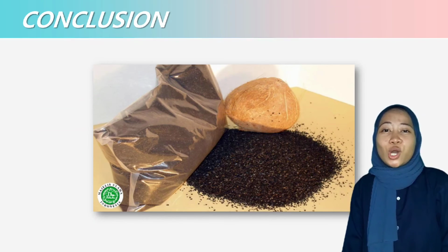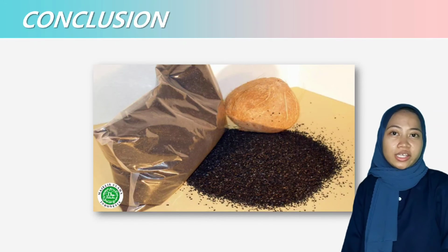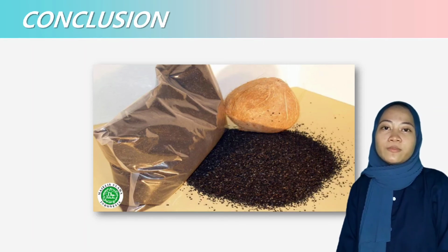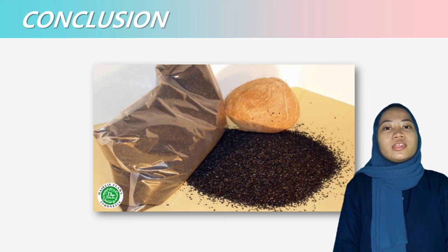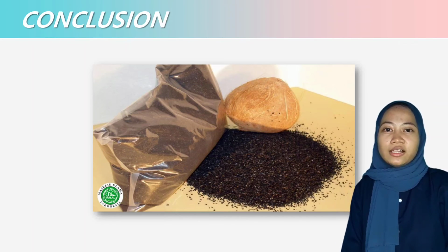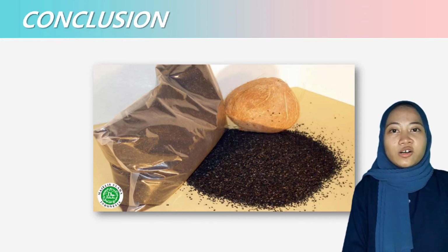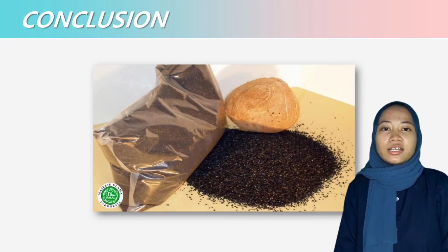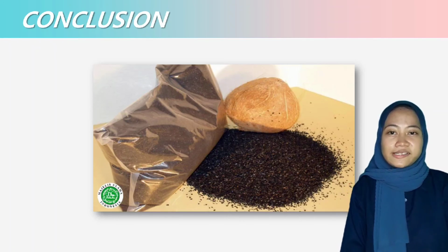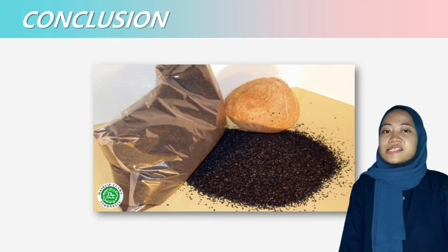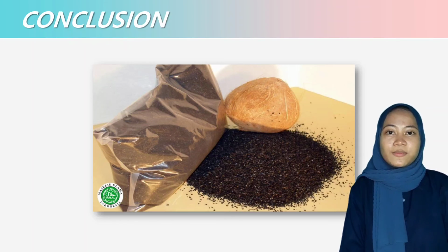So, it can be concluded that the highest efficiency of BOD, TSS, and turbidity removal is achieved by using 300 grams of coconut shell activated carbon for 7.5 minutes. The removal efficiency of BOD, TSS, and turbidity reaches 64.6%, 77.8%, and lastly 78.46%.